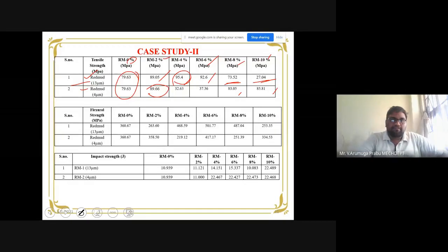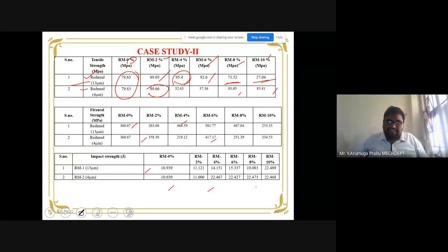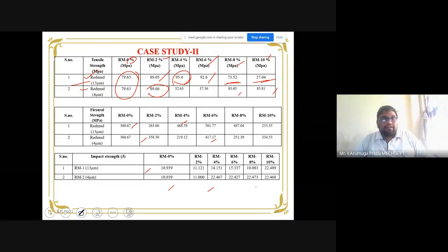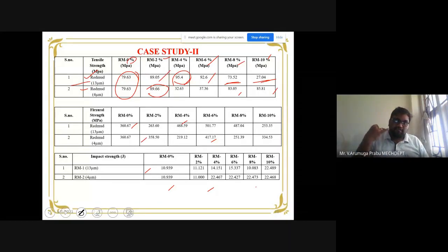Then followed by that, the flexural strength also behaves in such a manner. And the impact strength results are also shown in the table. So from these results, what I would like to conclude and insist strongly is that the addition of the red mud filler along with the natural fiber and polyester resin will produce an increase in the mechanical properties, that is, an increase in the tensile strength, flexural strength and impact strength.